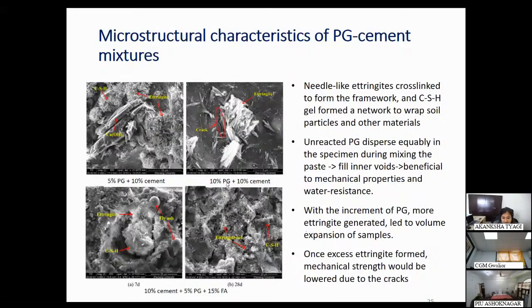But if it is 10% phosphogypsum and 10% cement, then it is seen that the ettringite collects there, and it is unreacted phosphogypsum. Since it is an expansive mineral, there is crack formation over here. You can see a crack near the ettringite.